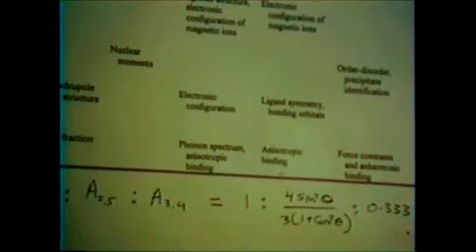A16, that means the relative intensity of the 1 and 6 peaks, because they are the same. A25, and A34, so the relative ratio of these is 4 sine squared theta divided by 3 times (1 plus cosine squared theta), 0.33. And theta is the angle between the gamma beam direction and the direction of magnetization. And all the time you know the direction of your gamma beam, and so you learn about the direction of magnetization in the material, which is very important also.